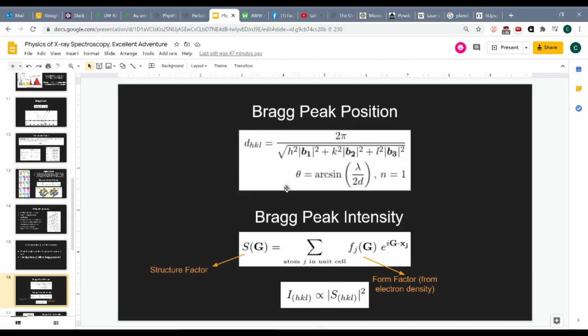And then to find the Bragg peak intensity, we're going to come up against something known as the structure factor. Now, a rigorous derivation of this would take about 2 hours and uses Fermi's golden rule and involves a relatively complex Fourier analysis. If you want to, we can go into that afterwards, but for right now, I'm just going to have to let this be fact. So the structure factor is kind of like the probability amplitude in quantum mechanics. The absolute value of the structure factor squared will give you the intensity that you will see. And it's defined for some value g, which is in terms of HKL.